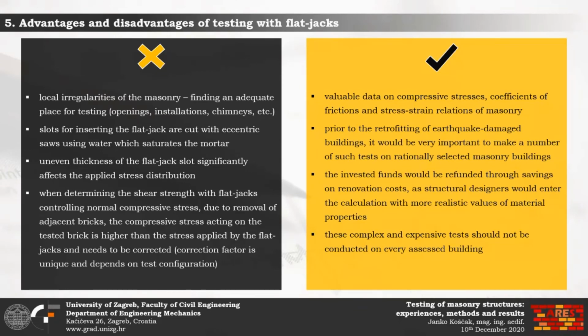Lastly, regarding the flat jack, I want to mention some advantages and drawbacks of such tests. Regarding the disadvantages, it's sometimes hard to find an adequate place for testing due to local irregularities of masonry. Slots for inserting the flat jack are often cut with eccentric saws, which use water, and that procedure saturates the mortar, so that's of course bad. Further, the uneven thickness of the flat jack slot can significantly affect the applied stress distribution. However, despite the mentioned drawbacks, valuable data can be gathered with such tests.